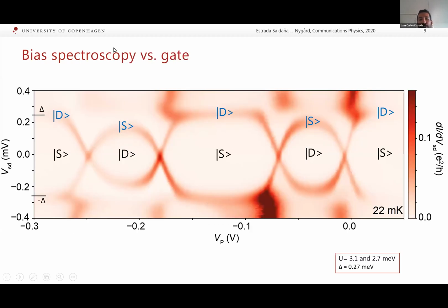So now that we saw how they look at a fixed gate voltage, let's see how they look as a function of the plunger gate of the quantum dot, which tunes the addition of electrons into the quantum dot. So then we can see that they make loops as the ground state changes from singlet to doublet in the small loops, and then to singlet in the big loop, and then to doublet in the small loop. And the lines that we're seeing are because of excitations. For example, this is an excitation from singlet ground state to doublet, which crosses zero bias to change the ground state to doublet, with a doublet to singlet excitation. And these are our parameters.